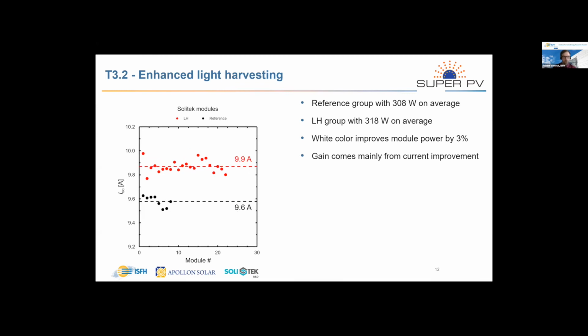And when we have a look at the short circuit current, we can also really see here the short circuit current for the same group. So black is again the reference, red is the light harvesting modules. And we can see that this gain really comes from the optical improvement due to the light harvesting in our modules. And also these modules are currently tested on our test sites.